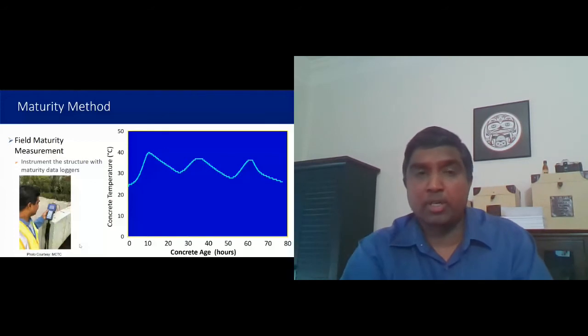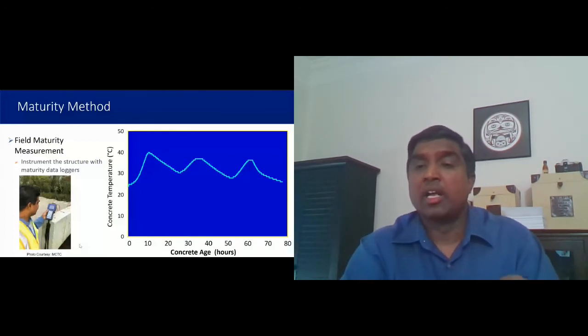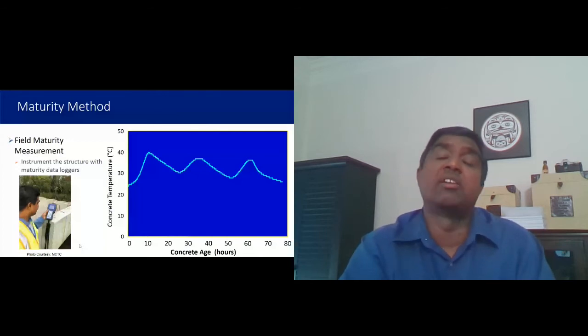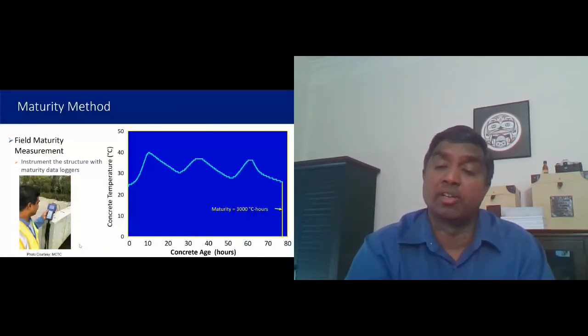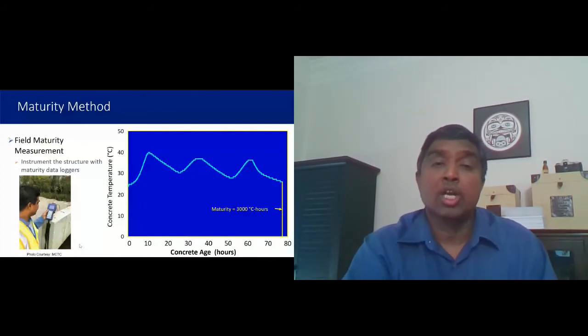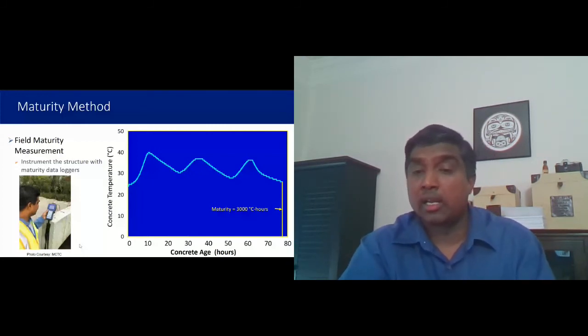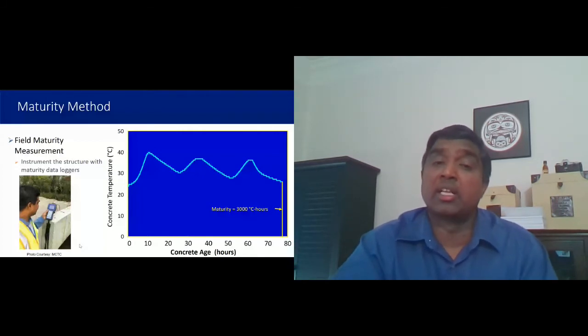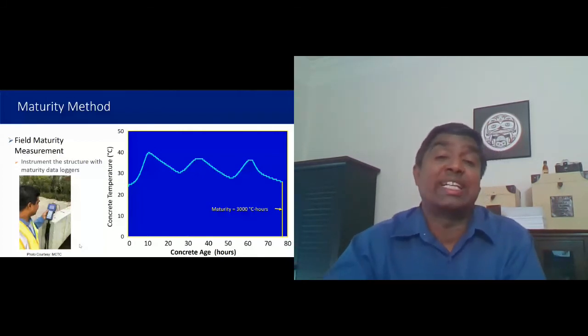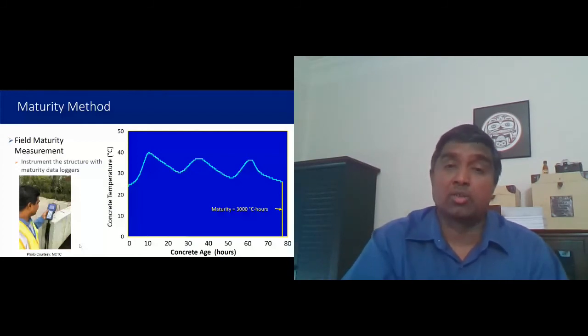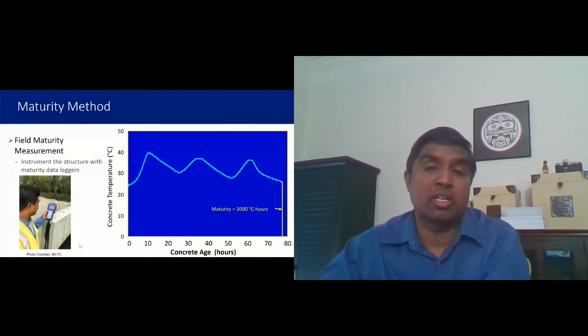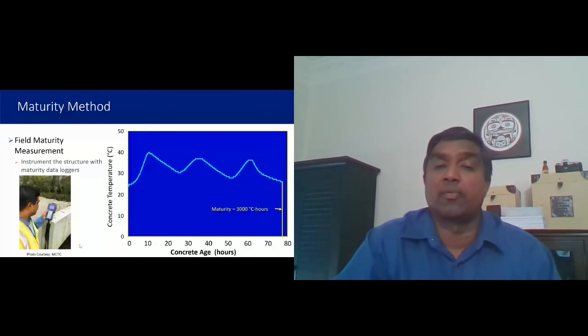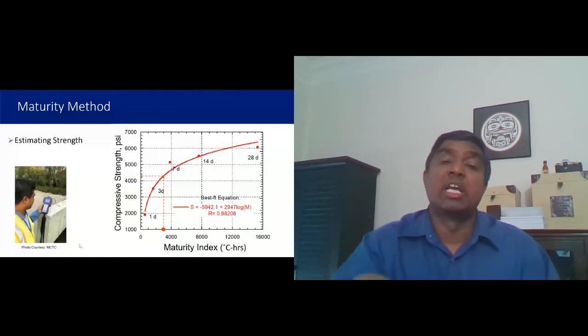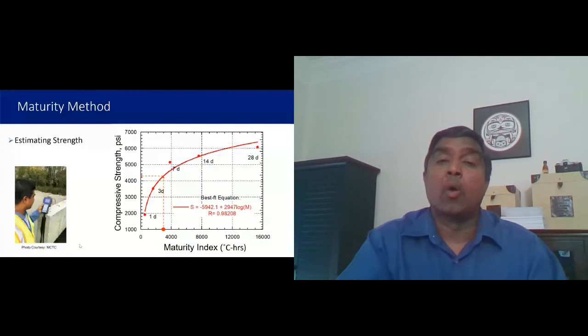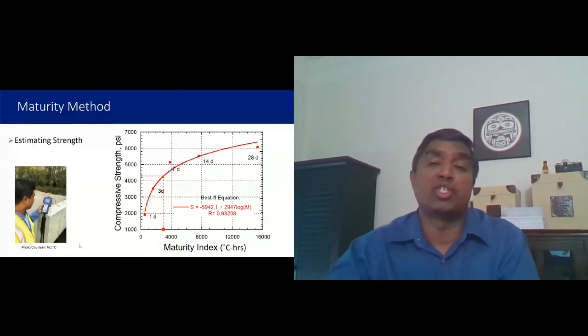And as you could see for this particular picture on the left, the maturity that I see there is 3000 degrees C hours. So those are the units that we measure maturity in, degree time and temperature, right? So degrees C hours. So then we go back to the calibration curve and look for 3000 degrees C hours of maturity. And then the corresponding compressive strength in this case is 4300 psi. So isn't that cool? At any given time, as soon as we know maturity, we can easily estimate the in-place strength of the concrete. Now, we can also do the reverse, which is if we know the compressive strength we are shooting for, we could then estimate the maturity number that we should be shooting for out in the field.